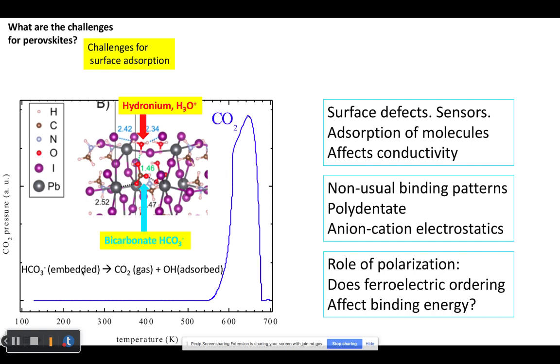So in this little work, the carbon dioxide binds with residual water on the surface, forms bicarbonates such as in soda drinks, and then it holds tightly because these hydronium and bicarbonate ions replace natural anions and cations of perovskite, and Coulomb electrostatic holds them really strong until one heats the sample up to a noticeable temperature.